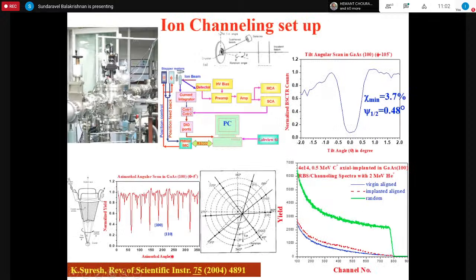And this is our typical ion channeling system. We have a 6-axis sample goniometer where we can mount the sample inside this vacuum chamber, and the sample can be tilted about the beam axis and also rotated. The goniometer stepper motors are automated, and different methods are available for aligning. We follow the method given by Professor Chu in his backscattering spectrometry book. In this, we mount the sample on the goniometer, and from the normal direction of the sample, we tilt.